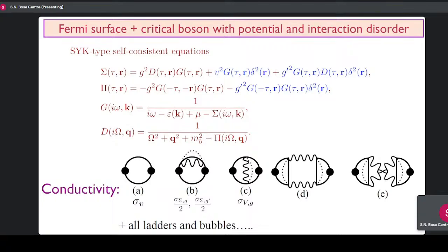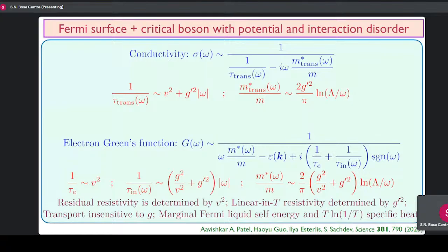We had enough experience with it that it didn't take too long. We solved this. You can also put it on a computer and solve these equations. But I'll skip all of that and just tell you the basic results. The basic result is that we get, at least qualitatively, just about every property that's observed in the strange metal. You get a conductivity that falls off as 1 over omega. That's exactly what optical conductivity results show. You get a resistivity that's a linear function of temperature, and you get marginal thermodynamic behavior: the electron Green's function, the specific heat is T log T, and so on.